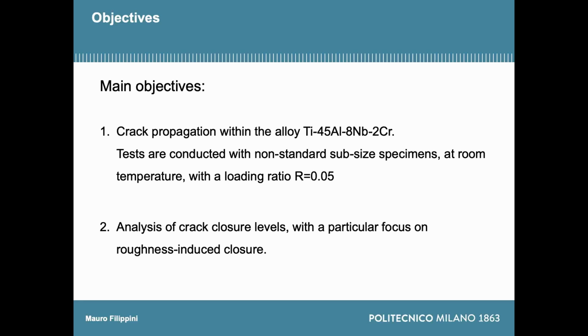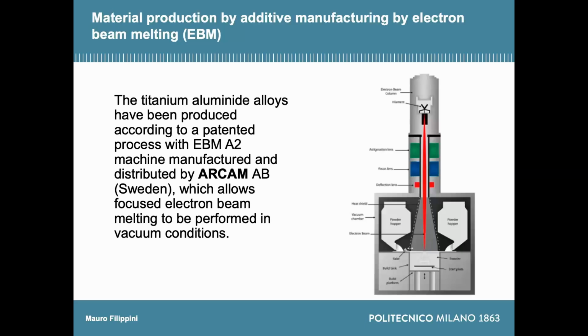So the main objective of this work is to highlight a few things. This is basically a side activity, a secondary activity we have performed on a high niobium alloy. So you have 8% of niobium, 2 chromium, around 45% of aluminum, and the rest is titanium. We have conducted this test with a non-standard subsize specimen, at room temperature with a loading ratio of about 0.05. And the main goal is to assess or to try to understand how closure plays a role in the fatigue crack growth threshold.